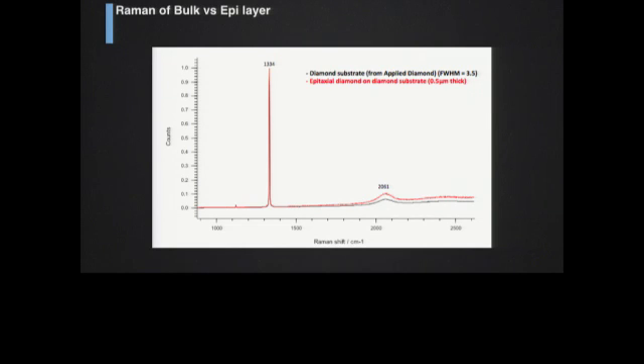So this is the bulk material plotted on top of the epitaxial material. You see a little peak out here. This represents some graphitic component to the substrate, a very low percentage. You see that the full width at half max for both the as-grown and the bulk substrate are pretty much almost identical to each other.